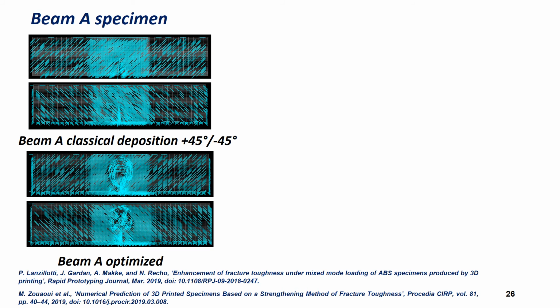Now let's check the validity of those identified constants on a complex geometry. For different printing configurations, bending specimens are chosen. Classical specimens at plus and minus 45 degrees, and optimized ones, are printed, and the numerical models are oriented. The following figures show the oriented mesh elements of both numerical models.